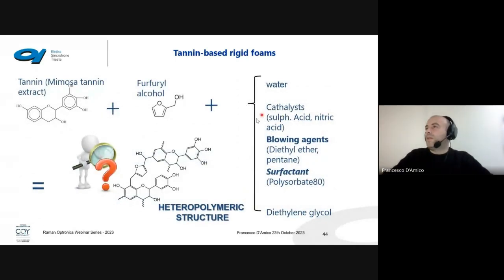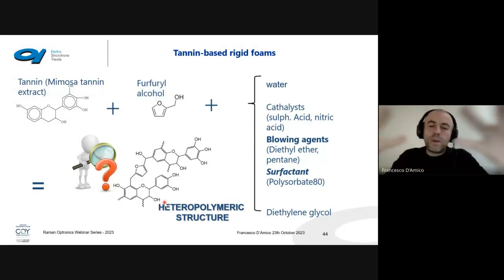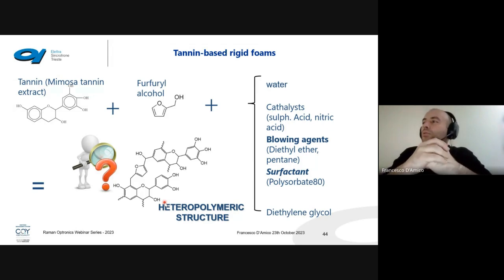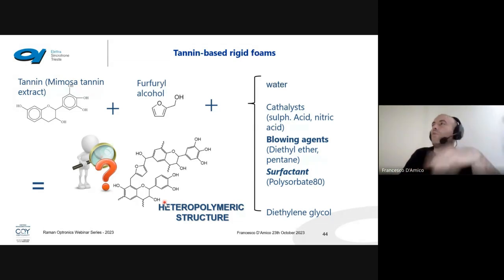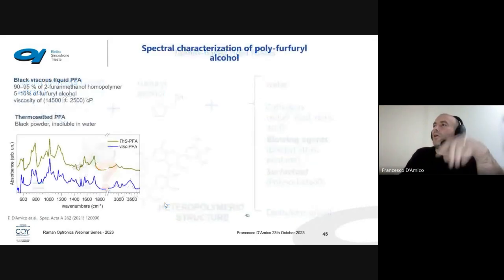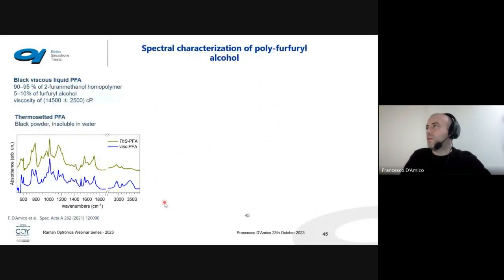What is done? Basically, we put two main ingredients, mimosa tannin and furfuryl alcohol, we make catalysis, we use blowing gas and a surfactant, diethylene glycol, in a small amount, and we finally have a heteropolymeric structure. The problem is that the macroscopic properties of these foams are related to their heteropolymeric structure. How can we determine the heteropolymeric structure of such a complex system? By employing more than one spectroscopy.